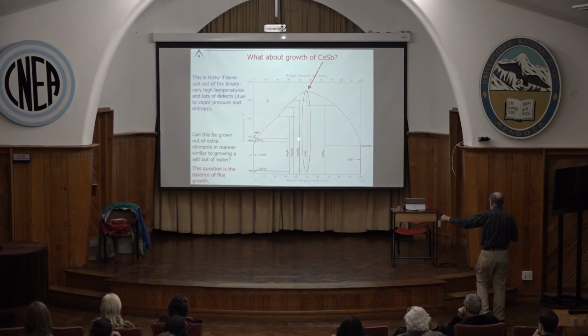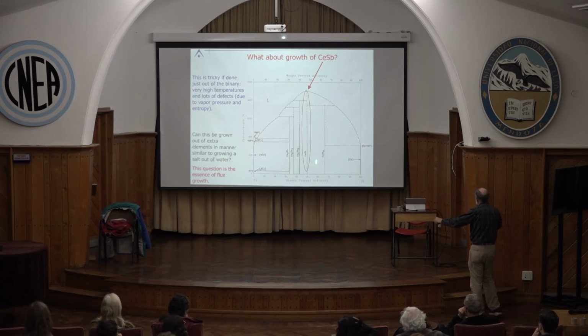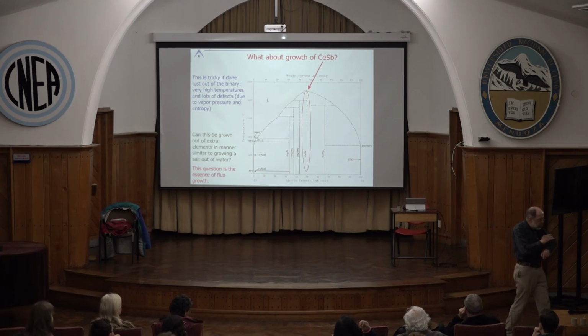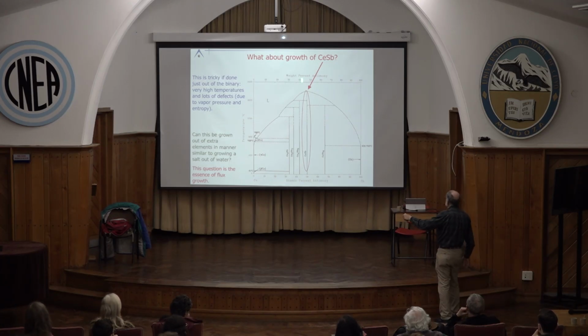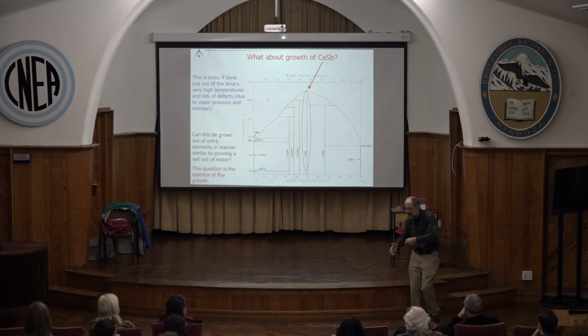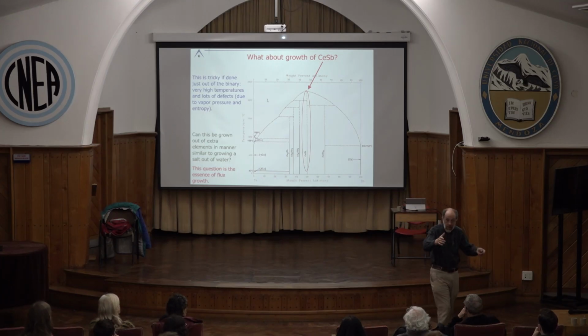What about cerium monoantimonide? And this is sort of going back to part of what you were saying. Look, this is a beautiful material. Oh my God, it's rock salt. It has more magnetic phase transitions than you can throw a rock at. I think it has 20 different magnetically ordered states. It's fascinating. But if you wanted to grow it just by solidifying the melt, you'd have to be around 1,800. You'd have huge vapor pressures. Things would be attacked. It would be very entropic. So lots of entropic disorder.